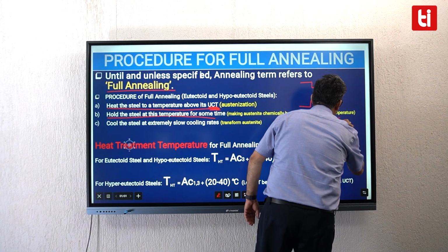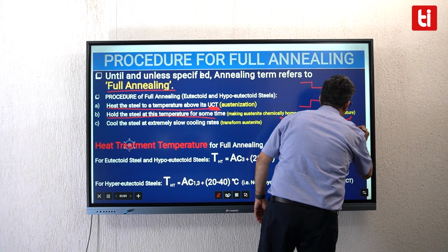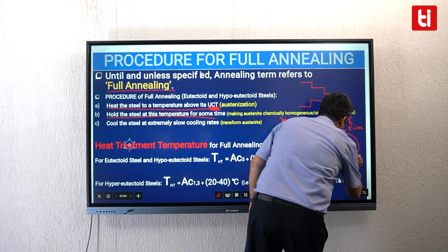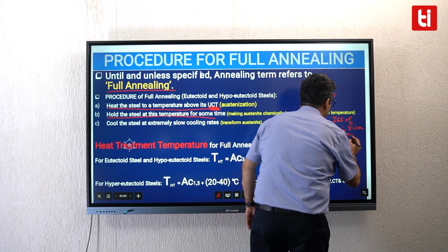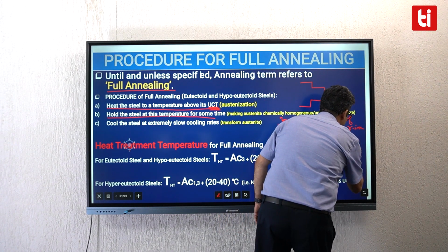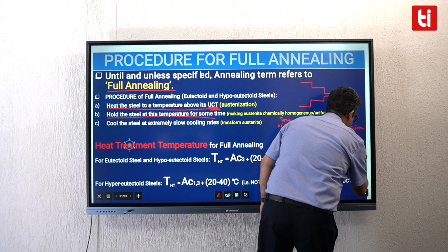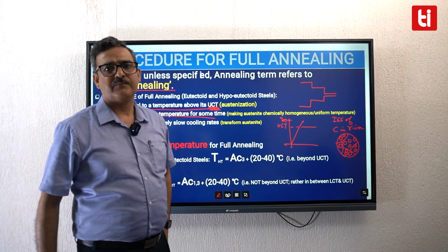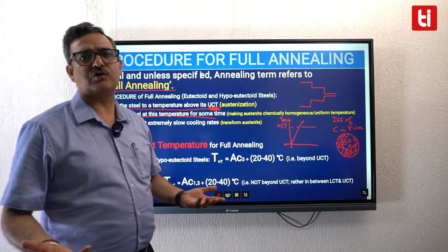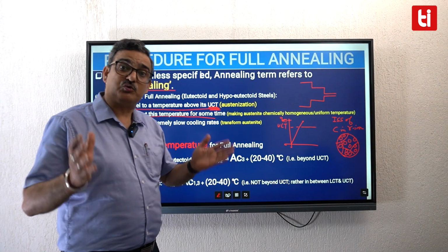Austenite is an interstitial solid solution. It is a solid solution of carbon in gamma iron. So at the heat treatment temperature, grains have got formed, grain boundaries are seen, but this austenite at some places has got more carbon. This is depicted like this schematically. And at other places it has got less carbon. तो गामा आयरन में कहीं कार्बन ज़्यादा है, कहीं कम है. तो भाई दिस केमिकल हेट्रोजेनिटी कैनॉट बी टॉलरेटेड. आपको इसको ठीक करना पड़ेगा.